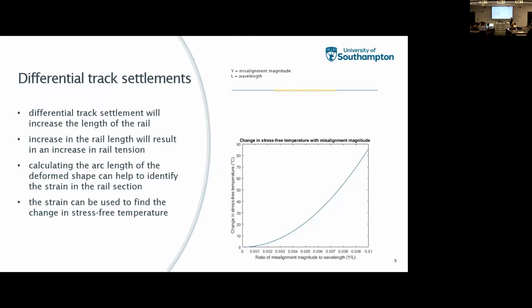I decided to have a closer look at track settlements. And as I said before, due to these track settlements, the rail tends to bend vertically to fill in the gap in the ground. So we can say that differential track settlement increases the length of the rail, and an increase in the rail length will result in an increase in the rail tension. And calculating the arc length of the new deformed shape, we can identify the change in the rail sections and find out the change in the stress-free temperature. So that's what I've done.